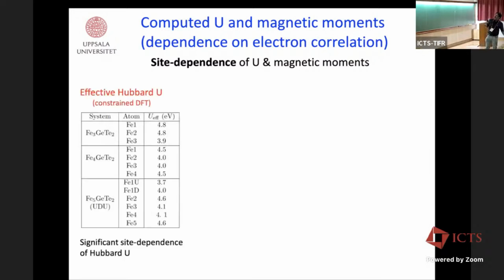So then we calculated the effective U from constrained DFT calculations. You see the corresponding calculated values there. They're site dependent also, because there are two equivalent iron atoms in the Fe3, and another one is separate. So you see that there are site dependent U. If you go to the Fe5, they are very much site dependent. That means it's not a good idea to just take one value of U and put it for all the iron atoms.